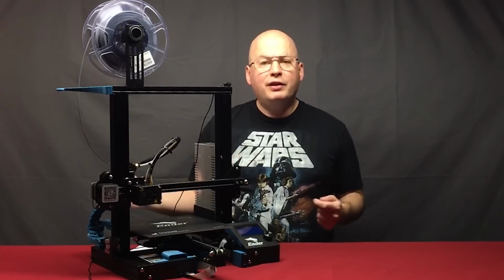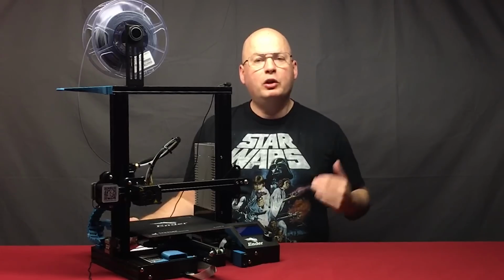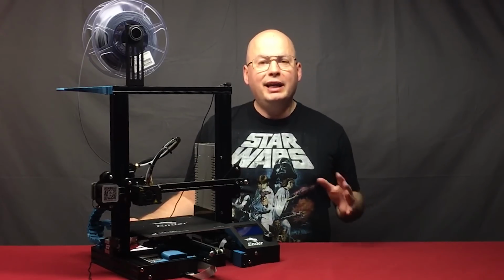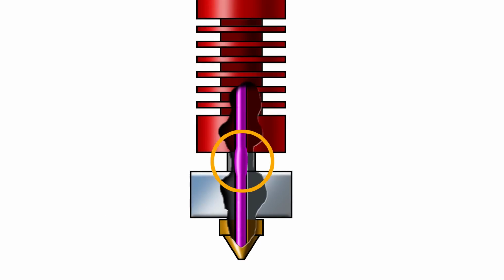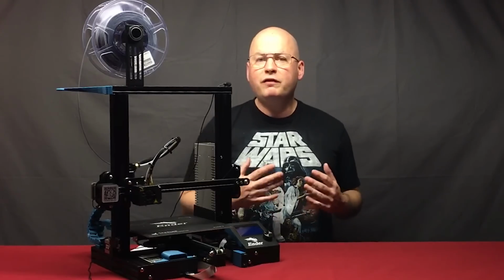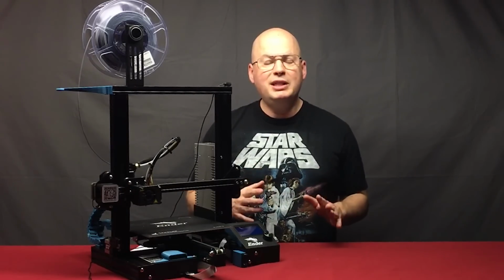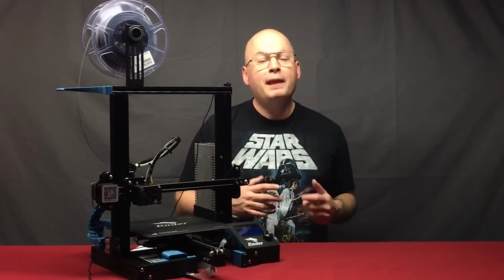When you have too high of a temperature, you get heat creep going up the length of the hot end into the areas that should be cool. The plastic, where it should be solid, starts to deform. It's reached its glass transition temperature and it bulges. That causes drag and it can't be pushed cleanly through the system, resulting in less filament coming out and under extrusion. So again, if you're adjusting your temperature, go in 5-degree increments. It'll make it much easier to identify that sweet spot.